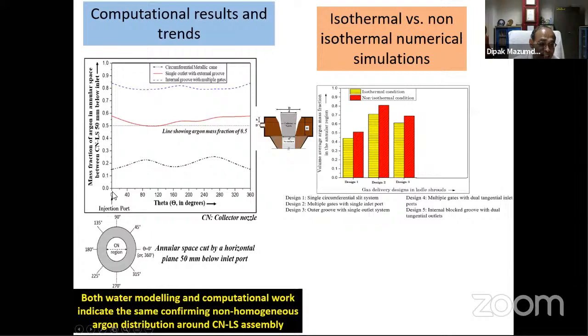This distribution is somewhere along a circumferential line, and you can see theta is equal to 0 to theta is equal to 360 degrees. It is somewhere here. If you pick a line, and on this line, along the circumference, you move on, how is the variation of argon? It shows that among the 3 designs, there is quite a bit of difference. In this particular case, we have barely 15% argon remaining at that particular height. We have 85% oxygen, and the best design that we have is something around 80% argon and 20% oxygen, or 20% air. And this figure, whether you carry out isothermal, which is yellow, or non-isothermal, has been reflected clearly. So it tells us that water modeling investigation indeed gives us a reasonable idea, albeit qualitatively. And the differential features of the three designs have been brought out very nicely by the numerical computations.